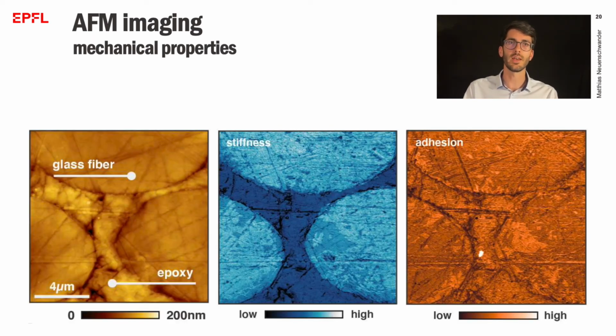Alright, to conclude, I wanted to present an image obtained with our cantilevers that shows some of the mechanical properties that can be extracted in off-resonance tapping. The sample is a composite of glass fibers and epoxy. The topography is shown on the left. The blue image in the middle shows that the glass fibers are much stiffer than the surrounding epoxy. On the red adhesion channel on the right, we can see some sticky patches on the glass fibers. This means that some epoxy was likely smeared onto the glass fibers while polishing the sample.